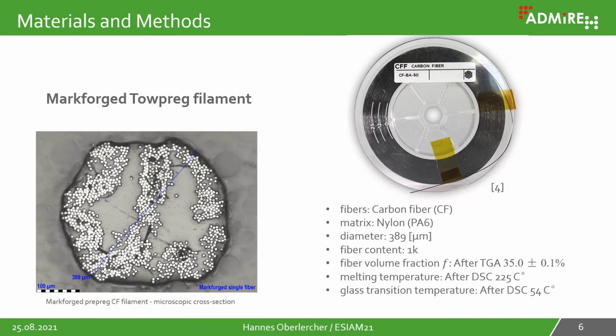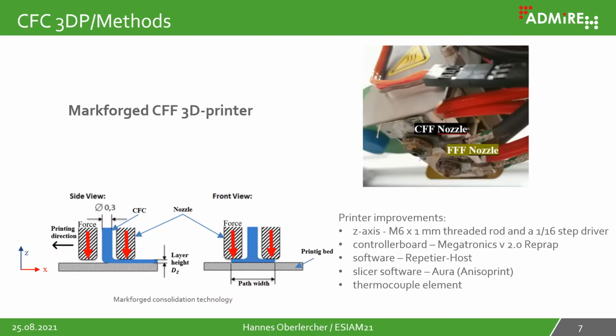The fibers are carbon fibers. The matrix is nylon PA6 material. The diameter is about 400 micrometers. We have 1000 fibers in the cross section. After thermogravimetric analysis, we determined a fiber volume fraction of about 35%. After differential scanning calorimetry, we have a melting temperature of about 225 degrees and a glass transition temperature of about 54 degrees.